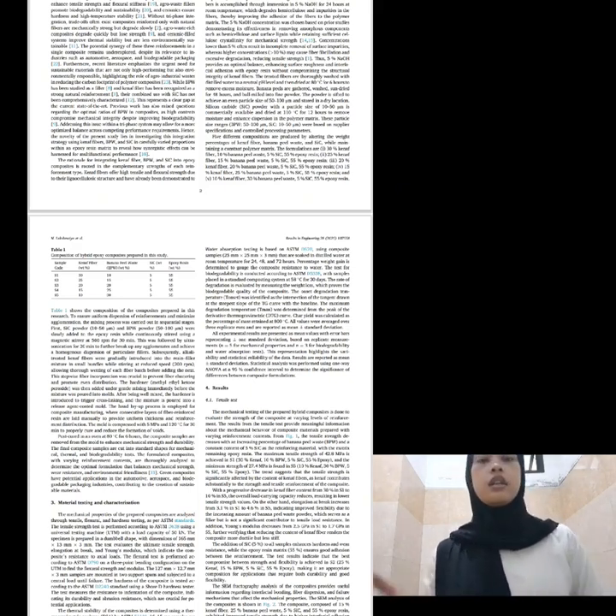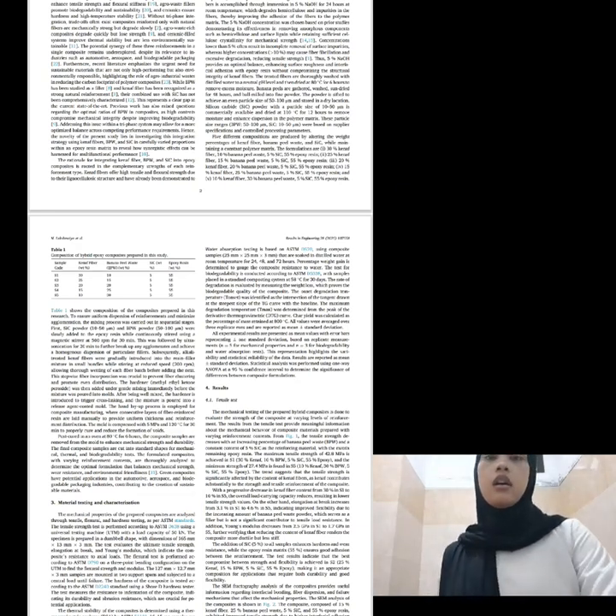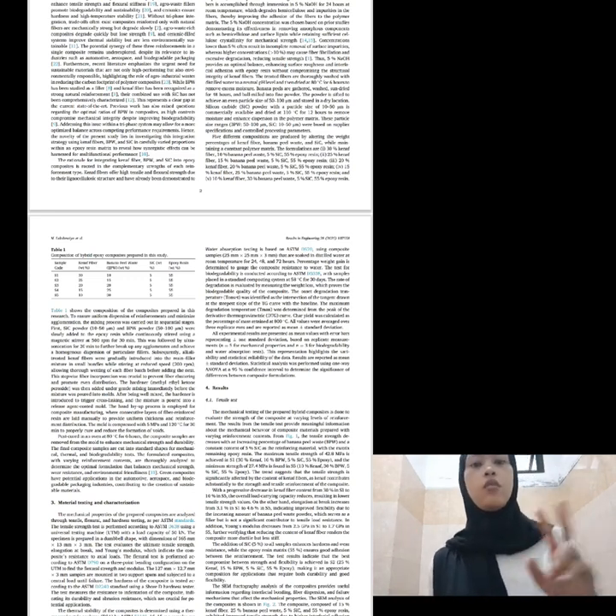Analysis methods. First, mechanical tests: tensile ASTM D638, flexural ASTM D790, hardness ASTM D2240. Second, thermal test: TGA ASTM E1131, water absorption ASTM D570, and biodegradability ASTM D5338, measuring weight loss over 30 to 90 days. Statistical analysis: ANOVA for reliability and error evaluation.